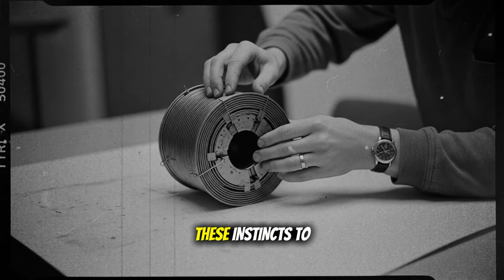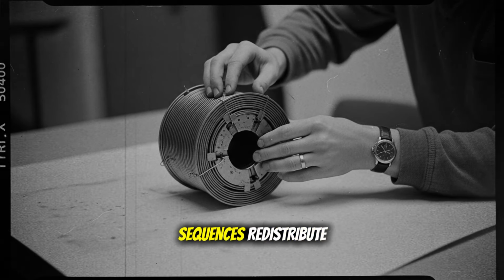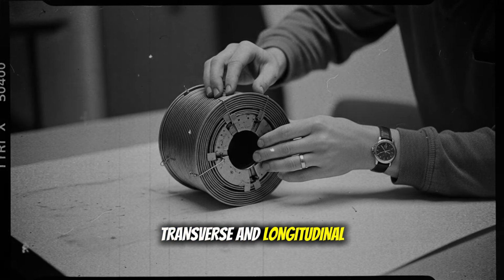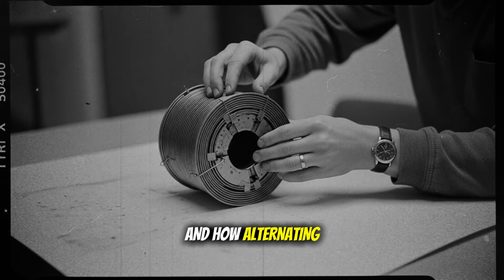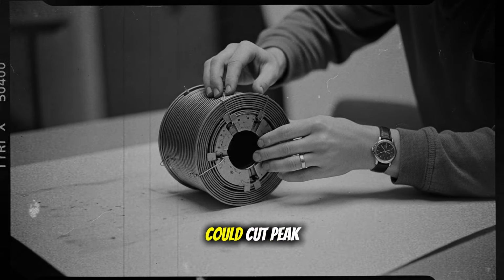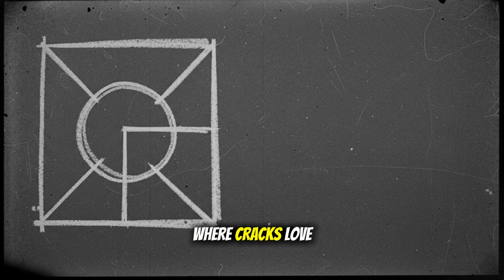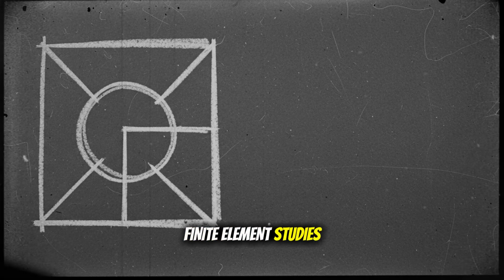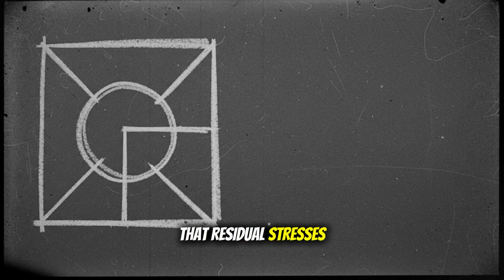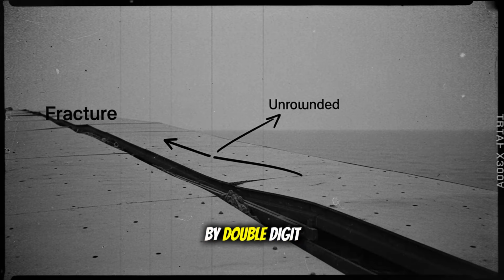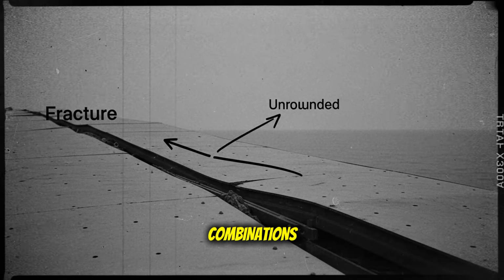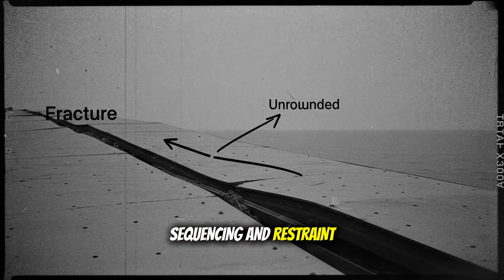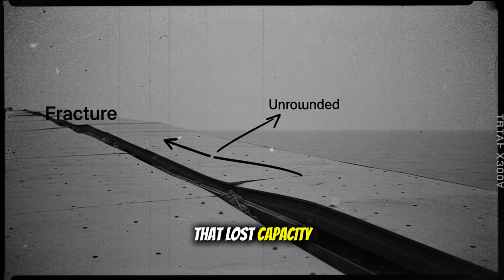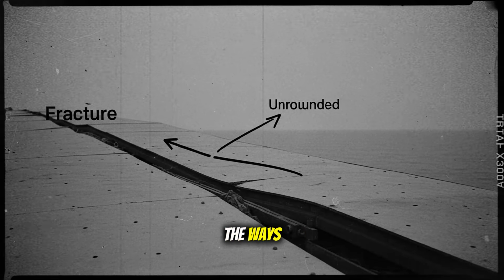Analysts later mapped these instincts to numbers, showing how different sequences redistribute transverse and longitudinal residual stresses, and how alternating weld lines or skip welding could cut peak stresses at the weld toe where cracks love to begin under cyclic bending at sea. Finite element studies on stiffened panels confirmed what fitters had sensed for months: that residual stresses and distortions reduce ultimate strength by double-digit percentages in the wrong combinations, and that controlled sequencing and restraint can recover a surprising share of that lost capacity before the hull ever leaves the ways.